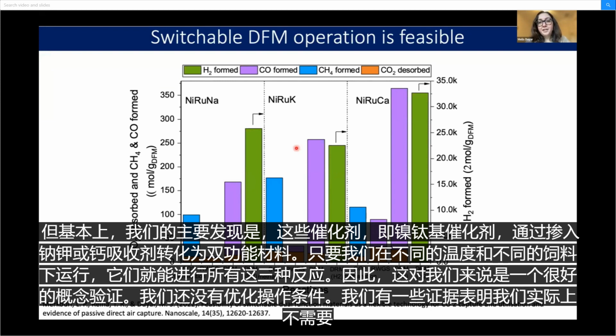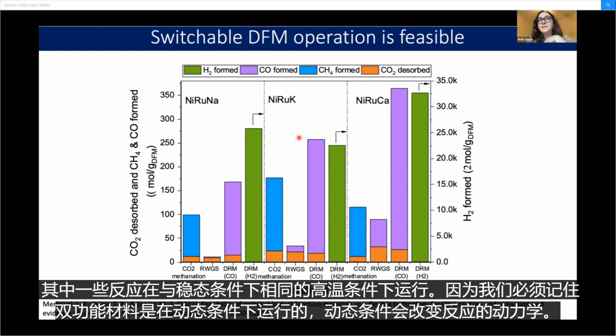But basically, our main finding was that these nickel ruthenium-based catalysts, when transformed into a dual function material by incorporating a sodium, potassium, or calcium adsorbent, are able to perform all three of these reactions, provided we operate at different temperatures and different feeds. So this was a nice proof of concept for us. We haven't optimized the operating conditions. We have some evidence that we actually don't need to operate at the same high temperature conditions for some of these reactions that we would under steady state conditions, because dual function materials, we have to remember, operate under dynamic conditions, which change the kinetics of reaction.